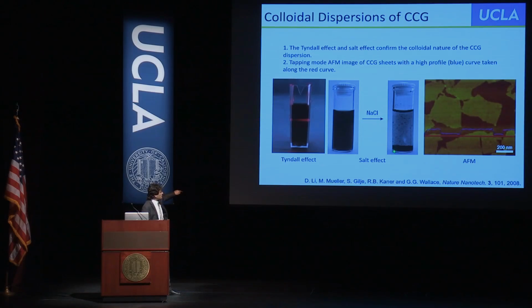So we have all these little particles, these little sheets of graphene, and they stay apart because every sheet is negatively charged. They don't like each other. Now, it's called a charge-stabilized colloid because if we add salt, the salt neutralizes the charge and they all flocculate out. You can see that here. And if you look by atomic force microscope, here's individual sheets of graphene. And if you run a probe along, you can see this going over. It's about 1 nanometer step height, and you can show that it's graphene.